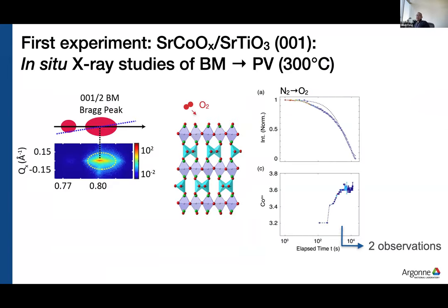On the left, I'm showing you the Bragg peak on a CCD. This is from the 0.5. This particular experiment is done at 300 degrees. We're essentially starting off in pure nitrogen, and at time zero, we're going to switch to pure oxygen. On the top right, you can see the intensity from the 0.5 as we switch to oxygen, and it dies off. It takes over 10,000 seconds to fully die away at 300.